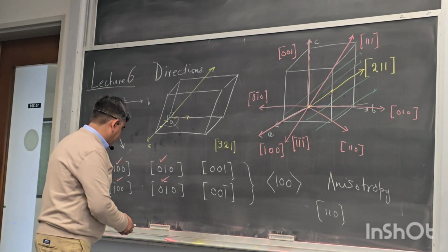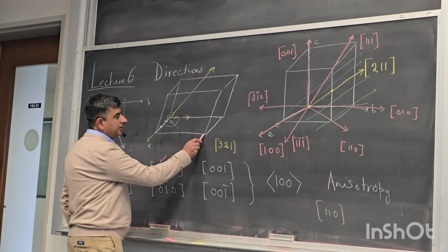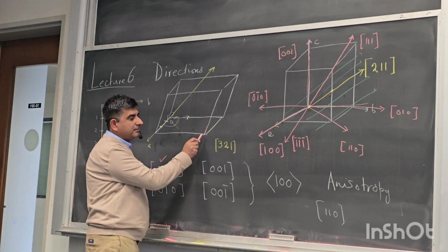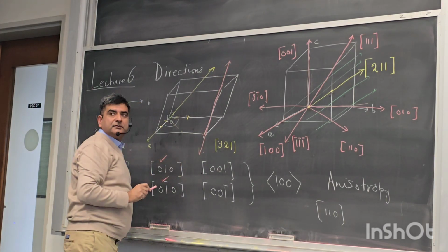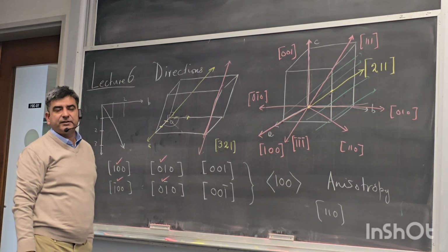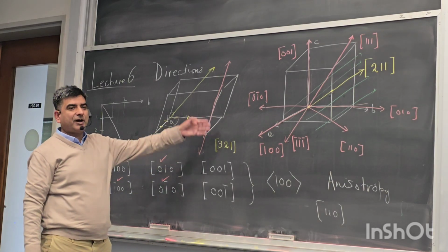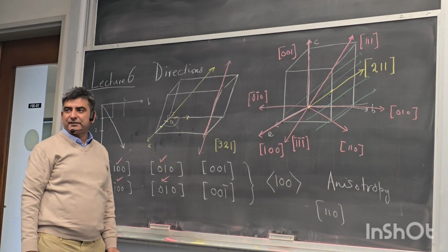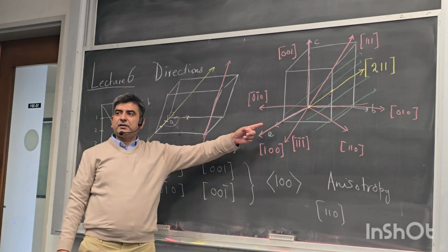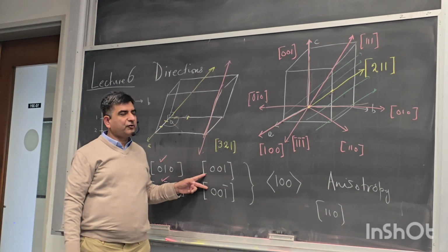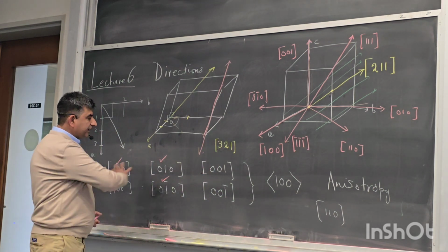No, they will. So this direction, in this monoclinic system, this direction and this direction are the same. They belong to the same family. There's really no difference whether you go up or down, because it's a lattice. And if you compare this with the 0, 0, 1 of the cubic, then these also form a family, but for cubic, all 6 form a family.